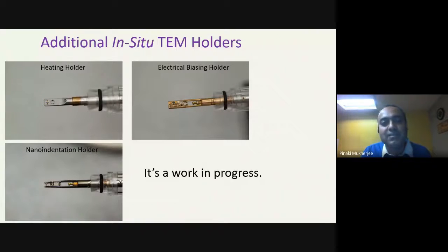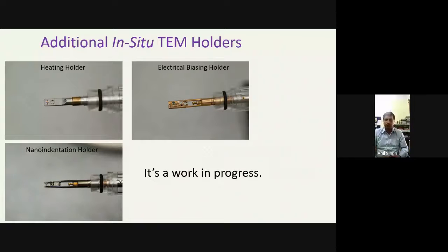So you get a correction factor out of that, and you can use that. And the fourth thing is below oxygen. If you try to measure those elements quantitatively, it's better to do EELS rather than EDS. Low atomic number elements.